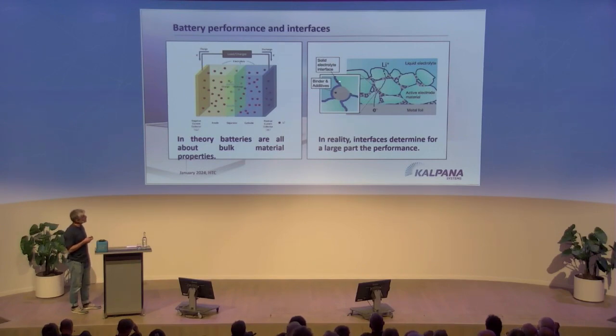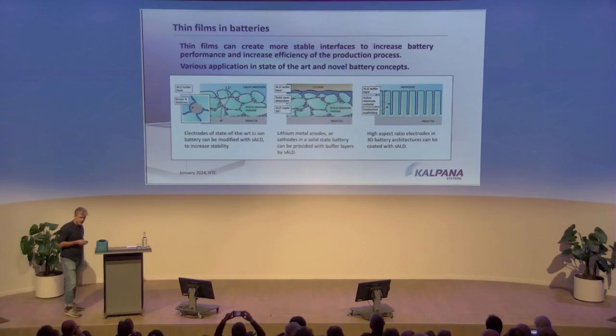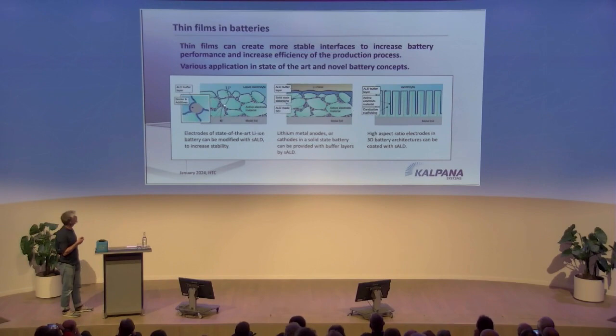And another thing is that when you start forming this interface, you use up a bit of the electrolyte and a bit of the electrode material. So actually the capacity even goes down when you start using the battery, just because of this. So if you can manipulate that interface with a thin film coating, make it more stable, or even completely avoid the formation step, and by formation step I mean growing this solid electrolyte interface, you can make batteries more stable, give them a longer lifetime, and also make them cheaper.